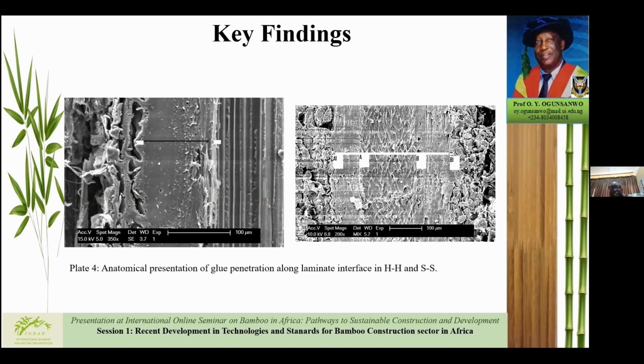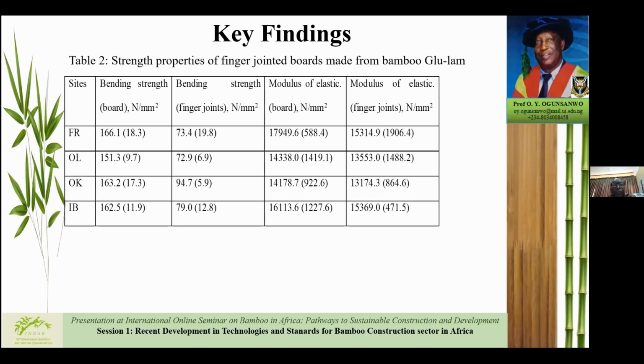What played out was that in the case of S and S, failure did not occur along the glue line. It didn't occur at the interface. It occurred right in the bamboo, in the inner side of the bamboo, outside the glue line, meaning that the bond between the 2 surfaces was too strong to be broken, whereas the bamboo itself was broken. So failure occurred where there's no glue line, and that's why you have a lower value in SS, not as a result of absorption of glue.